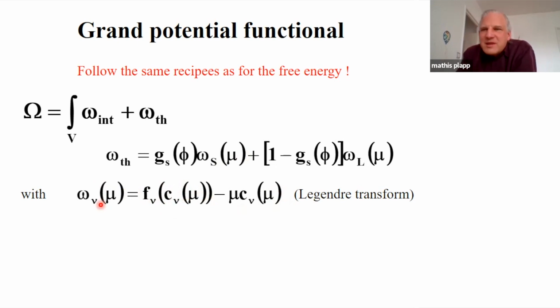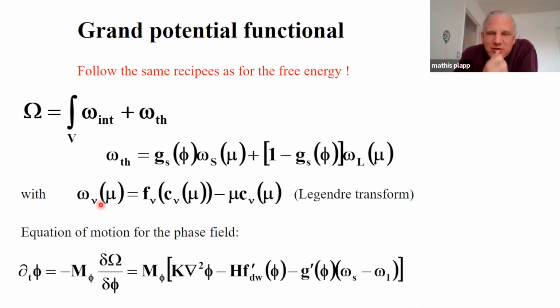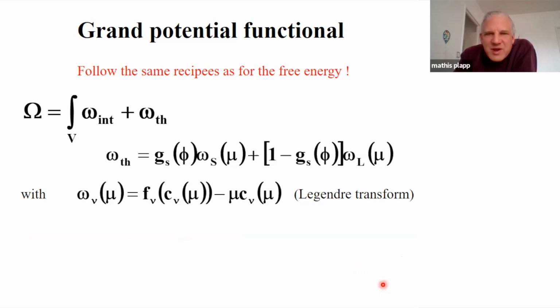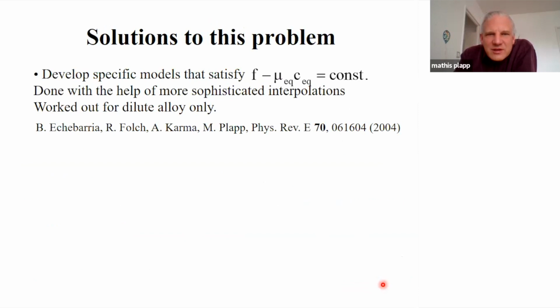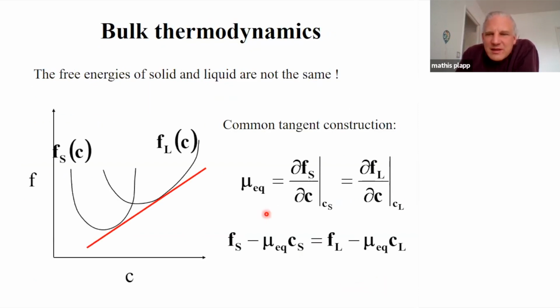So this is the classical mathematical trick of the Legendre transform. And if you then write down the equation of motion for the phase field, explicitly you get the interfacial terms as before. And now in the driving force, you get the difference between omega s and omega l. Precisely, if you remember the double tangent construction, you see that this is the omega s and this is the omega l, and in equilibrium they are identical.